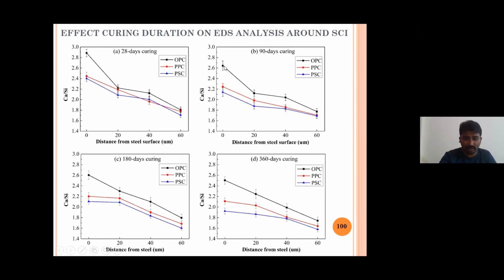At 90 days curing, all of them are reducing. See, for OPC it is 2.88, then it reduced to nearly 2.6. For this 2.4, then they are reducing also. This indicates that the calcium hydroxide content is reducing as I increase the curing period. What does that signify? It signifies that the calcium hydroxide is converting to some secondary CSH. So that might improve the bond strength. So we are curious to know what is the effect of this on ultimate bond strength, right?